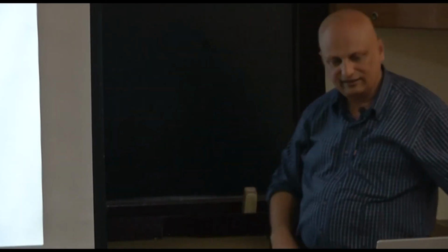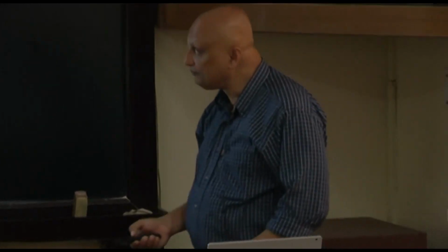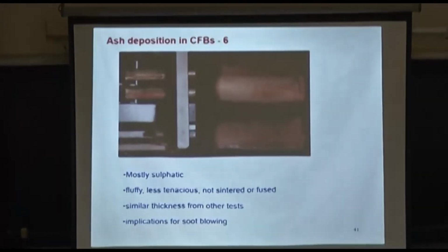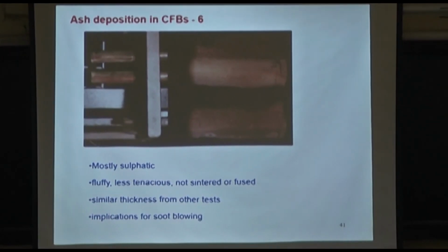So bed agglomeration, calcium oxide, no, it will not contribute. Where it will contribute is in here, because they will go and get a nice cool place to settle. And that's why I have said that when we analyzed this by SEM-EDX, these are mostly sulfatic. Why? Because of that.